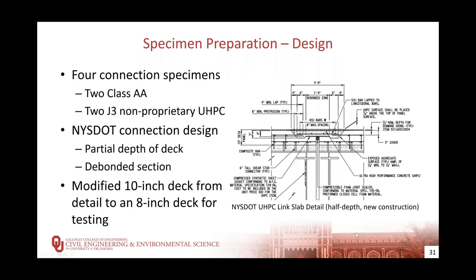So, for our tests, we constructed four specimens, two link slab joints with a class AA concrete and two with the J3 non-proprietary UHPC. As a reminder, class AA is the standard concrete mix for bridge decks used by the Oklahoma DOT. The design of the link slab connections was based on a New York State DOT detail for new construction. The detail calls for a 10-inch deck, but we modified the proportions for an 8-inch deck.